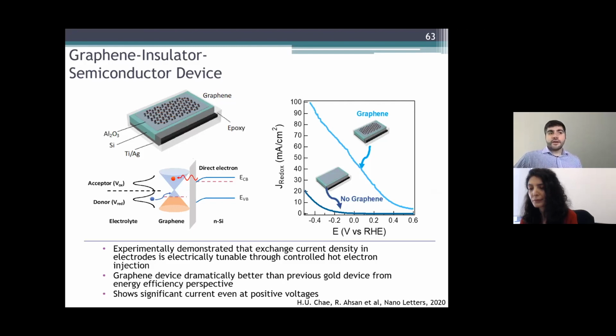So now, to generalize your question a little bit more beyond just zirconium dioxide and aluminum oxide, as you use different materials, what ends up happening is you have different tunneling barriers, and those different tunneling barriers will lead to different relative distributions of the voltage dropping across the oxide versus the semiconductor, which will then lead to different levels of hotness of your electrons, which are being injected into that top surface. So the answer is it does matter,